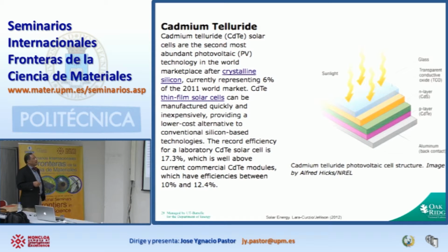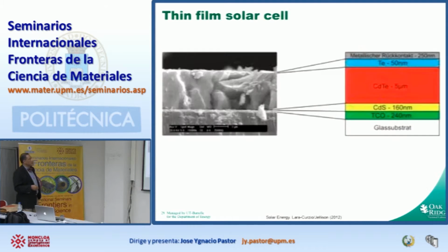Tomorrow we're going to be talking about critical materials. So there are some concerns with the mass production of these systems. The efficiency of cadmium telluride is around 17%. But again, the major concern with cadmium telluride is the fact that these materials may not be available, and these are toxic. So there are serious issues there. Same idea, you have glass on the top. This can be coated with an anti-reflective coating. Here you have your PN layer, cadmium sulfide, cadmium telluride to form your PN layer. And then you have aluminum in the back to collect your electrons.